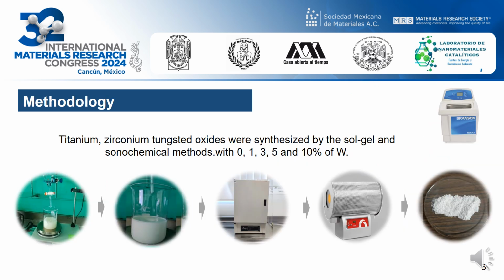The titanium zirconium tungsten catalysts were synthesized via the sol-gel method with a 1 molar ratio of titanium to zirconium. The amount of necessary salts was added depending on the balance carried out for the molar ratio, using two solutions. A solution with the necessary amount of acetic acid and distilled water maintaining a constant pH of 3 was prepared, and another solution was prepared with the mixture of titanium butoxide, zirconium butoxide, and 1-butanol as solvent, with the necessary amount of metatungstate at different tungsten concentrations such as 1, 3, 5, and 10 weight percentage.